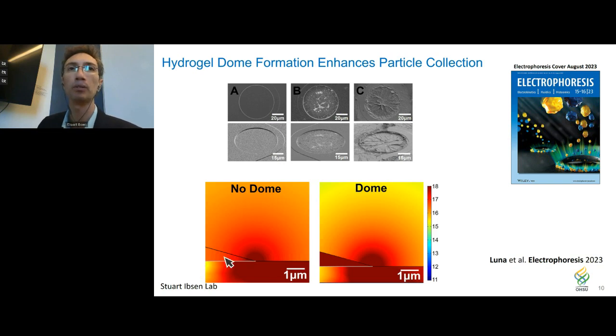And then down here, we have computer simulations showing the consequence of having these domes. Here we have a no-dome situation as opposed to one where the dome is present on the right. Here you can see the edge of the dome that we're modeling in this particular COMSOL model. The gradation from the red region to this darker orange color is a lot less of a gradient than what we see here, with this red region, which is a little bit larger, out to this yellow region of electric field intensity. So this shows us that we are getting a much higher field gradient because of the presence of the dome, as opposed to when there is no dome present. That can explain why we see better collection of particles in the presence of this dome formation. So it's a really great way to increase the amount of particles being collected.